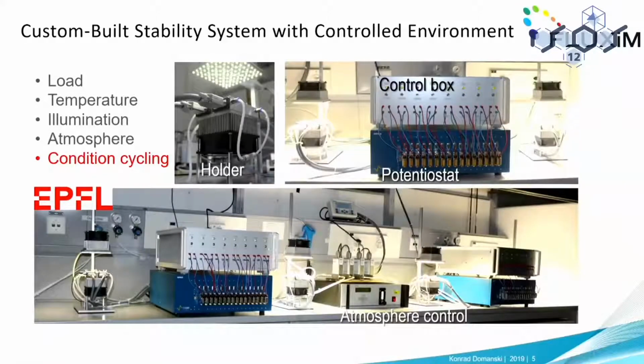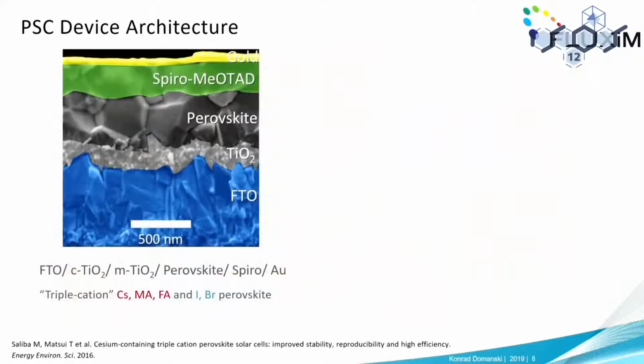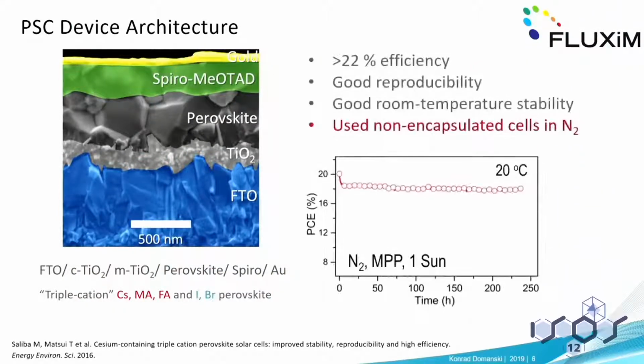So with that in mind, we modified our setup, which could already do very low temperature and illumination atmosphere control, to also do condition cycling. And we used our workhorse device with FTO, titanium oxide, spiro, gold, which gives us good efficiency, good reproducibility, and behaves nicely at room temperature at maximum power point. And in this study, we only use non-encapsulated devices.